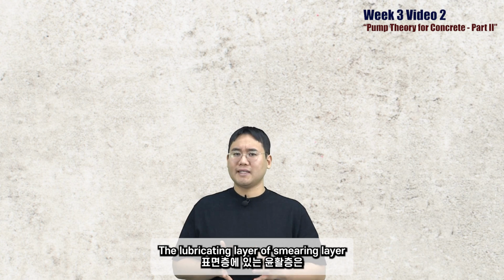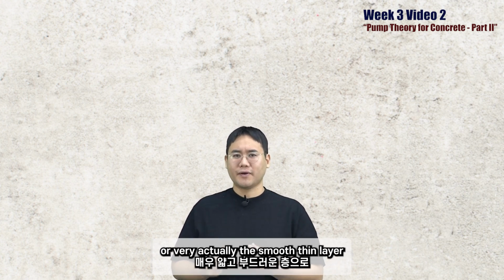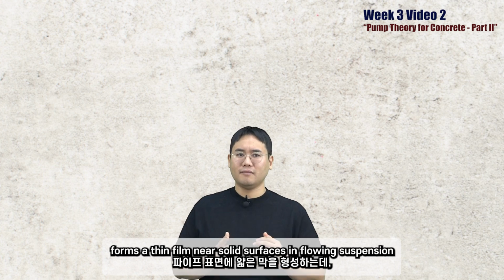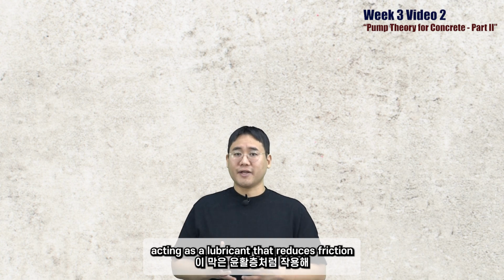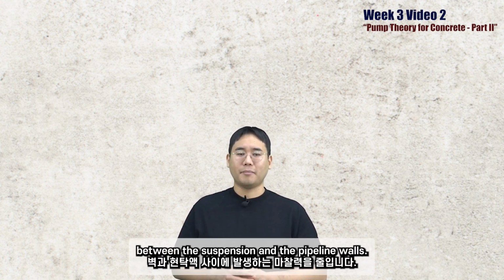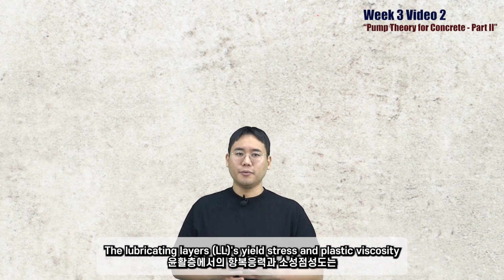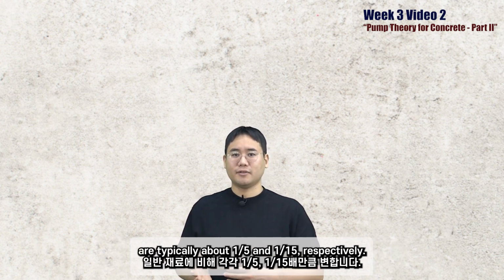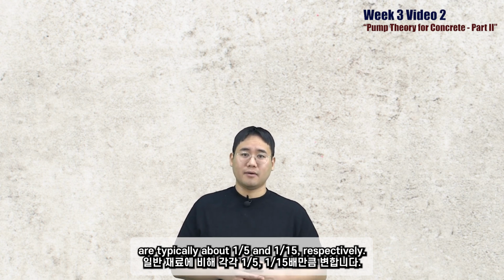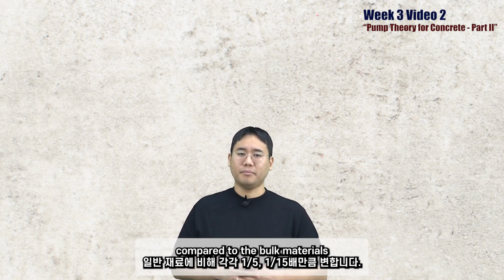The lubricating layer, or smearing layer, forms a thin film near solid surfaces in flowing suspensions, acting as a lubricant that reduces friction between the suspension and the pipeline walls. The lubricating layer's yield stress and plastic viscosity are typically about 1/5 and 1/15, respectively, compared to the bulk material.